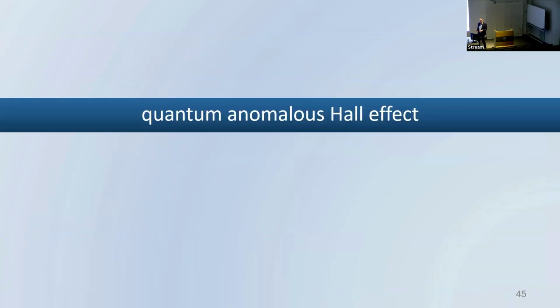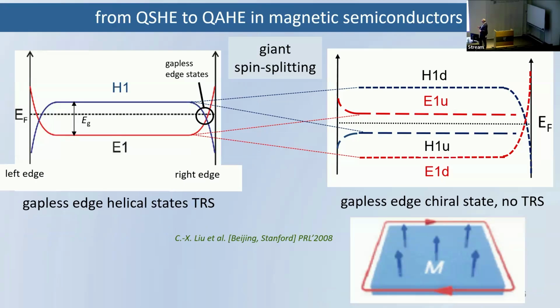And now we turn to another quantum effect, the quantum anomalous Hall effect. Now we ask the question, what happens if we have a quantum well like that, where time reversal symmetry is conserved, and we add a lot of magnetic impurities so that we produce huge splitting of this conduction band and of the valence band, which are inverted. Here it's p-type, it's anion, and here are cations.